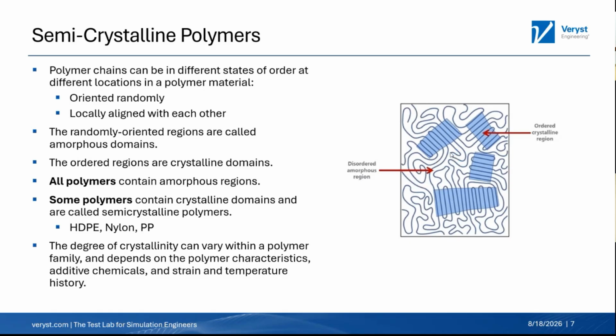But some polymers have some domains, which you can see here highlighted in blue, where the polymer chains like to stack in a specific local order that's called a crystalline domain. And so the crystalline domains in polymers that have them tend to impart things like higher strength and higher creep resistance, whereas those aren't present in those fully amorphous polymers. But the key distinction is that all polymers contain amorphous regions, but only some polymers contain crystalline domains. So that's why we call them semi-crystalline polymers, because they have both amorphous and crystalline domains. That degree of crystallinity can range from only a few percent of the material up to pushing 70, 80, even 90 percent of the material being in crystalline domains. Most engineering thermoplastics are a bit lower than that. But common examples include polyethylene, polypropylene, and nylon, some of which are commonly used in thermoforming applications.